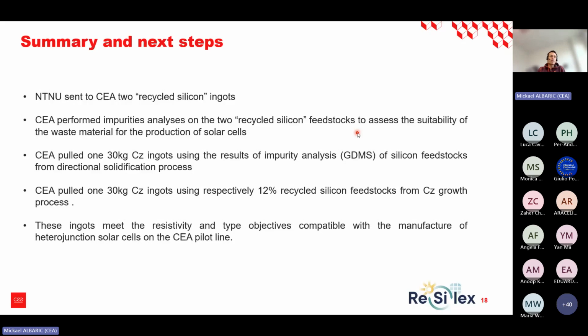CEA pulled one 30 kilogram CZ ingot using the result of the impurity of the GDMS of silicon feedstock from the directional solidification process. CEA pulled two other CZ ingots using the other one. And in the last case, we use 12% of recycled silicon feedstock. And all these ingots met the resistivity and the type objectives, which are compatible for the elaboration of heterojunction solar cells on our CEA pilot line.